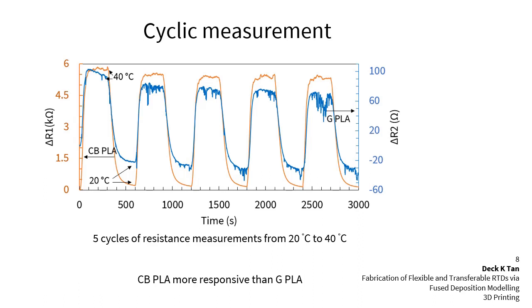Again, the sensors were placed on a hot plate and the temperature was set to increase from 20 degrees Celsius to 40 degrees Celsius. Then the change in resistance was measured for 5 minutes at every second, and after 5 minutes the plate was cooled down to 20 degrees Celsius.